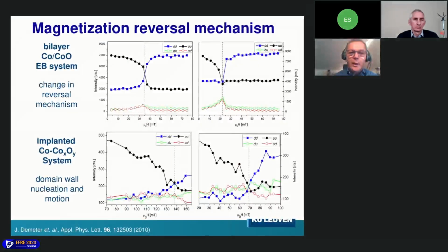Now, you can measure the magnetic depth profile by doing a reflectivity scan, but there is more that you can do with neutrons. You can also gain information about the magnetization reversal mechanism, meaning that you can see if there is domain wall nucleation and motion, or if there is a coherent rotation of the magnetization. And this you do by making so-called field scans. So that means that you stick to a fixed scattering angle and you measure this up and down neutron reflectivity as a function of the applied field.